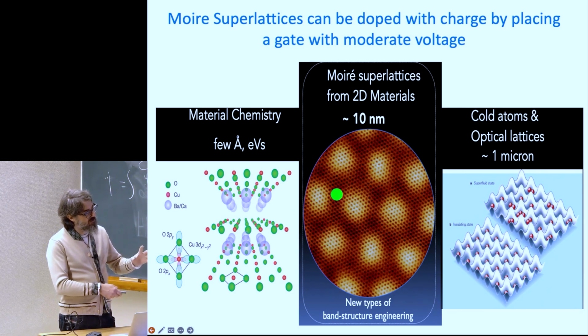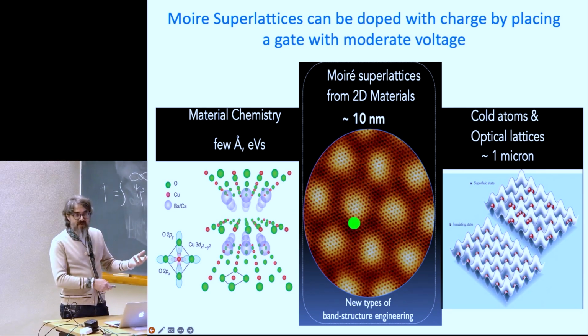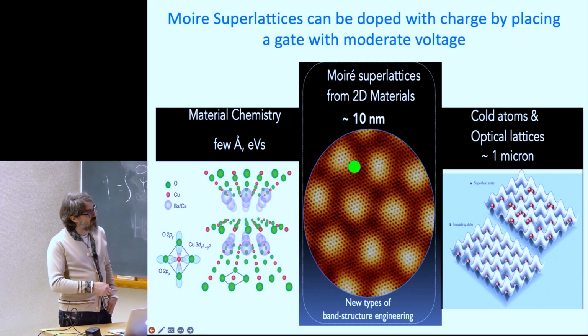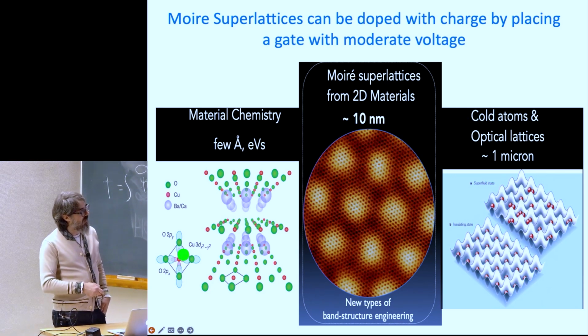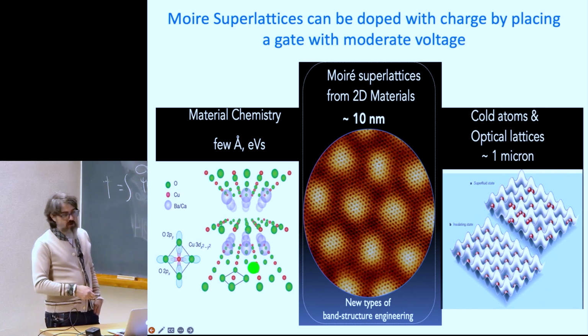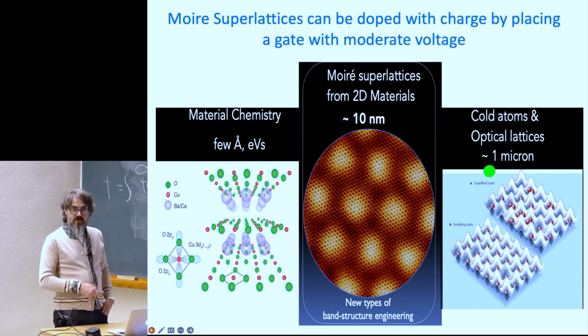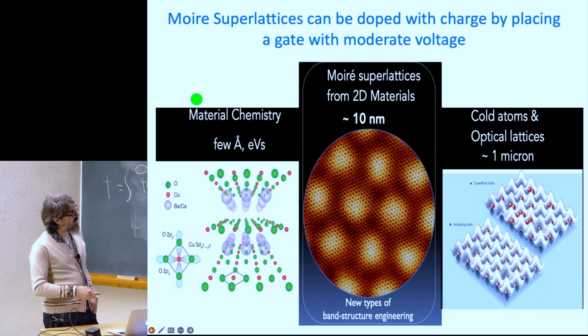This is a larger angle, but it's 1 degree. They're made of 10,000 carbon atoms, or electrons of the carbon atoms. So the effective degrees of freedom have a length scale of around 10 to 20 nanometers, okay, which really puts them in between cold atoms and material chemistry. But unlike cold atoms, these can have larger interactions. And unlike material chemistry, these can have larger controllability.